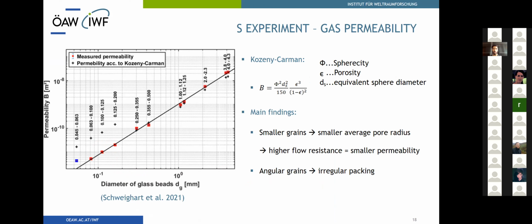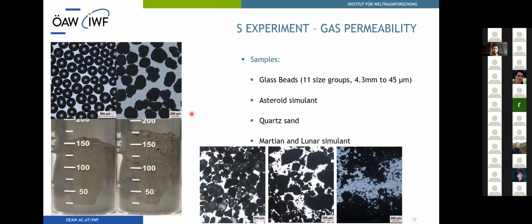If we look at the formula of the Kozeny-Carman model, the sphericity, a measure for the roundness of grains, enters quadratically. The equivalent sphere diameter relates to the ratio of a grain surface and volume. Even the porosity is affected by the shape of grains. As angular grains interlock more easily than smooth spherical grains, they can randomly create larger pore spaces, as could be seen on the images of the previous slide.